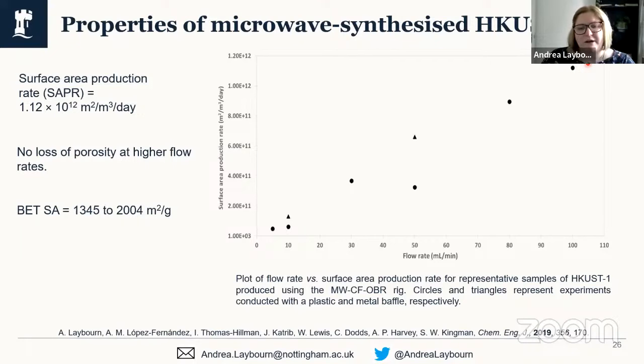So what this is showing is that not only are we producing a lot of material, but we are producing material which is very highly porous, and we're not getting any issues with loss of porosity, even at these exceptionally fast timescales. And to give you an idea of roughly the surface areas associated with these materials, we're in the order of around 1,300 to 2,000 meters squared per gram.